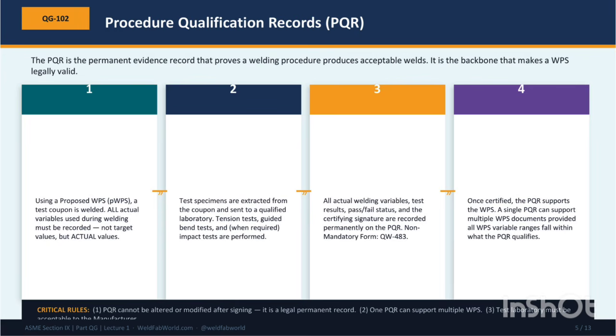Step 4. PQR supports the WPS. Once certified, the PQR formally supports the WPS. And here is an important and very practical point. One PQR can support multiple WPS documents, provided that all the variable ranges listed in those WPS documents fall within what the PQR qualifies. Conversely, one WPS can be supported by more than one PQR. For example, if you used multiple test coupons to establish different thickness ranges.